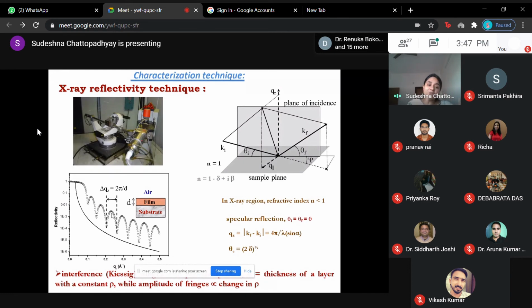So our estimation will be erroneous. But if it is below that, the technique will be great. Of course, as you have understood, if these fringes get very close, that will be a problem. On the other hand, if the fringes become very broad, maybe when the film thickness is 1 to 2 angstrom, that will again be difficult, because the separation of these dips will be too wide. Then your background will come, because after 8 degrees, at low angle, your background will come and you will not get the real dip. So you cannot estimate, because at least 2 dips are required to get the film thickness. So very low is a problem and very high is also a problem.